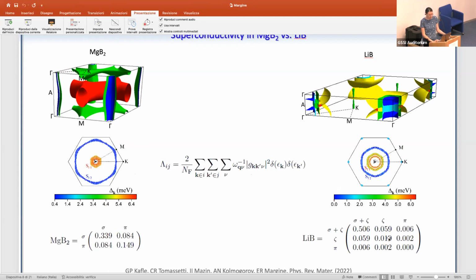There is some minor contribution coming, at least in the decomposition, from the lithium states, and the dominant coupling in this case is from this sigma and NFE state. So I should have mentioned, this is the Fermi surface and this is the cross section. So in this 3-band model, we included in the first zone the sigma states that are slightly coupled with the lithium states. Then in the second region, the states coming from the lithium, and then the outer part would be the pi states.